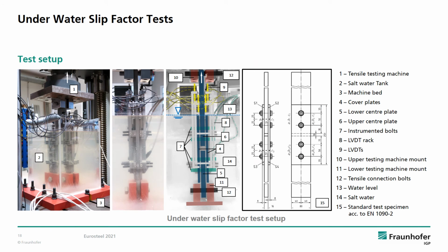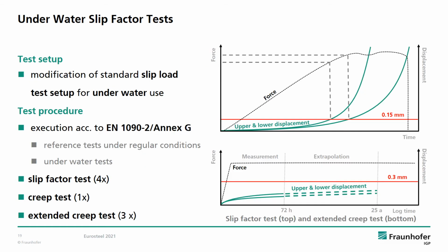For underwater slip factor testing, we basically put our regular slip factor test setup inside a saltwater tank. Slip factor test specimen consists of two center plates and two cover plates held together by 4 bolt assemblies. During testing, the center plates are mounted in the testing machine and torn apart vertically to determine the coefficient of friction of the plate surfaces. Our test procedure was based on the specifications given in Annex G of EN 1090-2. For reference, we determined the slip factor under regular conditions first, before we did all the testing underwater.